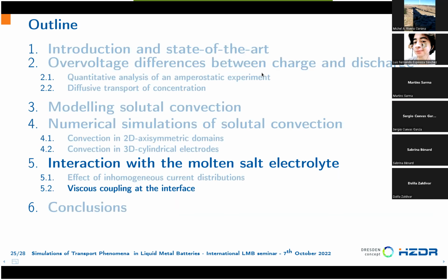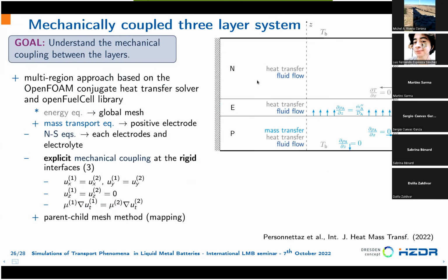And now I would like to focus on a slightly different effect, and this effect is the mechanical coupling of the positive electrode with the electrolyte, in particular in the other layer. So we study in this case solutal convection in the positive electrode, and we also solve fluid flow in all the other layers. To do that, we use OpenFOAM with a multi-region approach. And at the interface, we use an explicit coupling of the interfaces. So this means that we are coupling stress and the velocity at the same time.